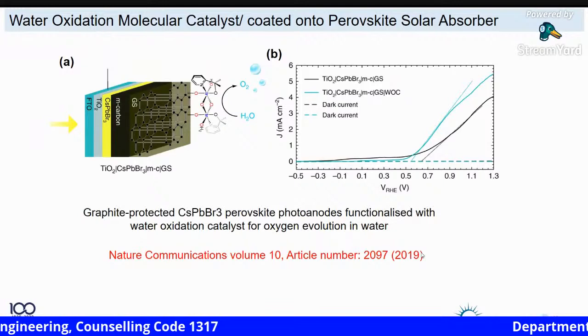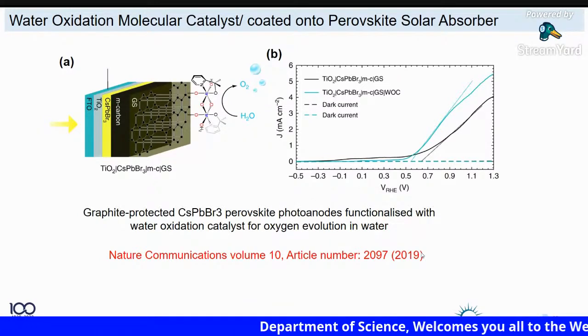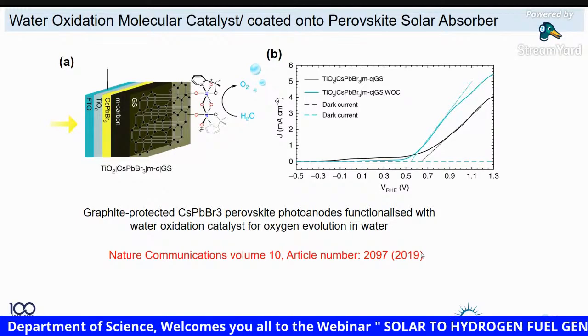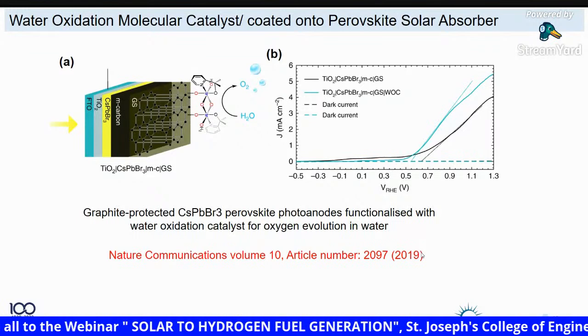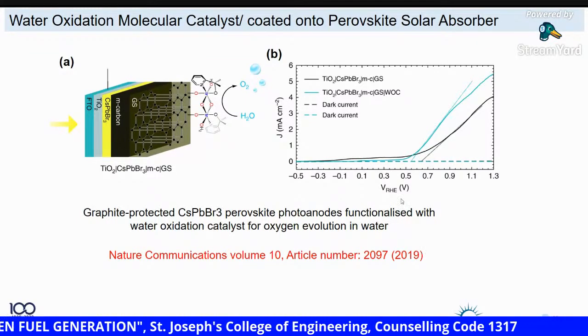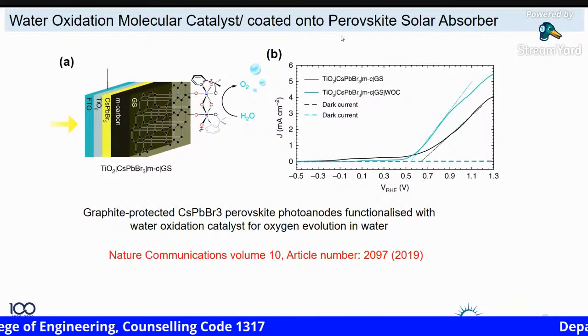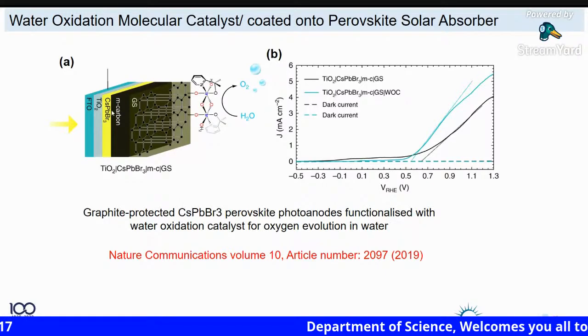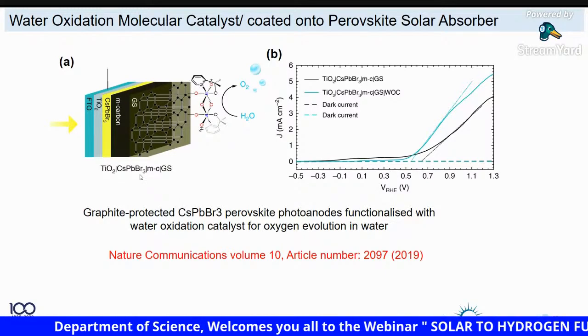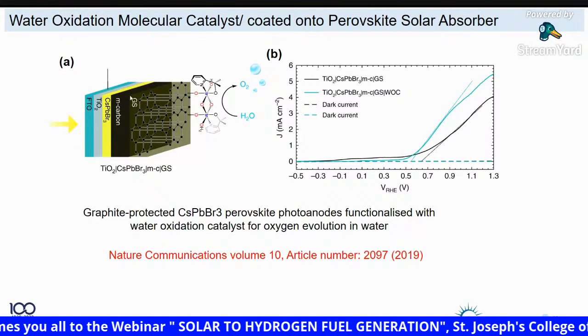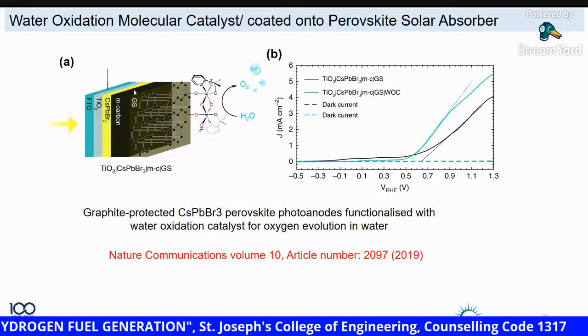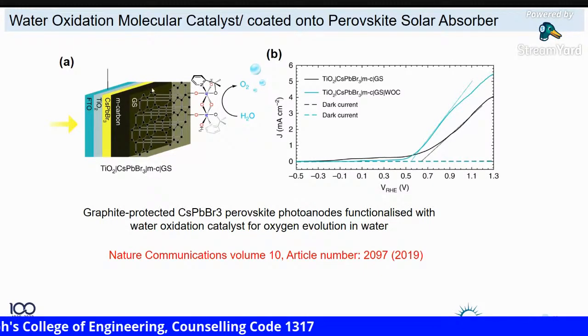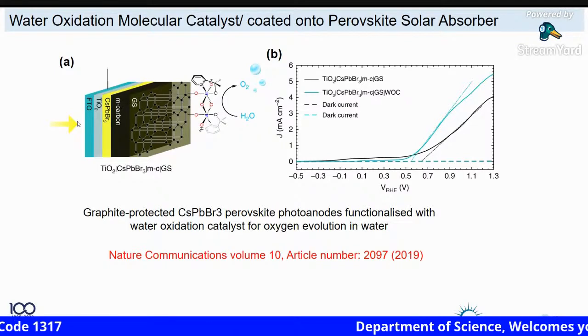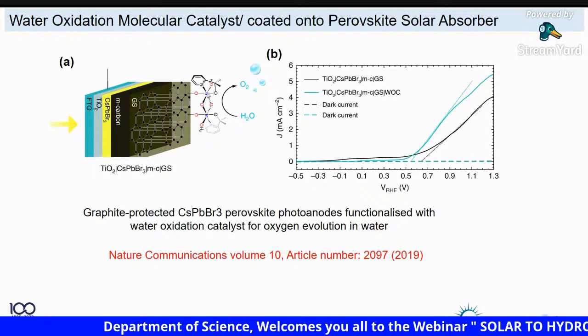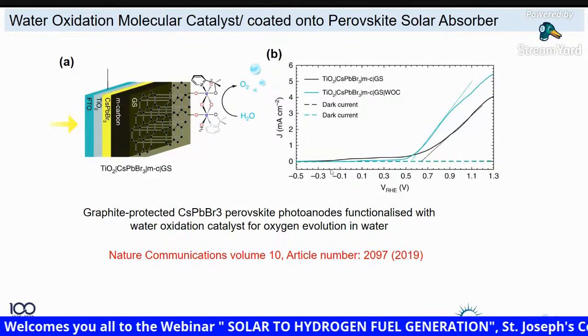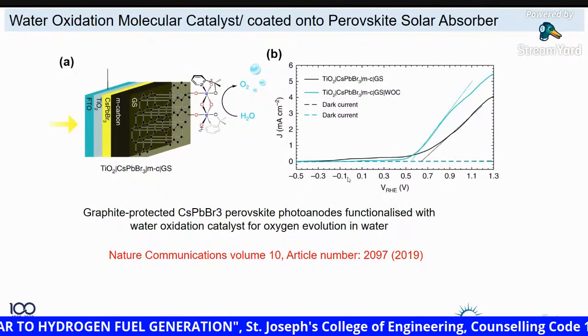So recently, most of you have heard about the perovskite solar cell, one of the champion solar cells coming very rapidly. The efficiency number progressively went from 5 to 21, 23, 24. But one problem, if you apply the perovskite solar cell here, it's not stable in water or humidity. Okay. So recently one of my colleagues in my department, Professor Tristan, in association with Bath University, UK, demonstrated that they coated mesoporous carbon on the perovskite structure, protecting the perovskite layer, and then coated, as I mentioned, some kind of co-catalyst on the top of the layer, and they demonstrated the current density in photoelectrochemical water splitting.